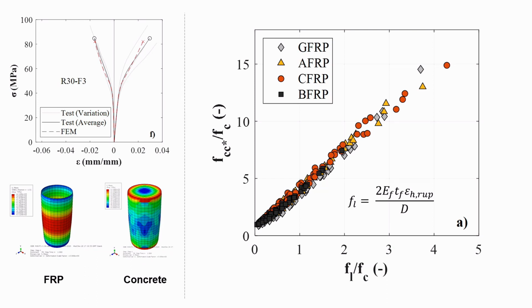Here I'm plotting the confinement effectiveness, which is simply the confined strength over the unconfined compressive strength, against the confinement ratio, which is a function of the FRP material properties. And we see a linear relationship between the two, which is just saying that the more confinement you have, the higher the strength. And this is not affected that much by the type of FRP. We considered glass fiber, aramid, carbon fiber reinforced polymer, and basalt fiber reinforced polymer.